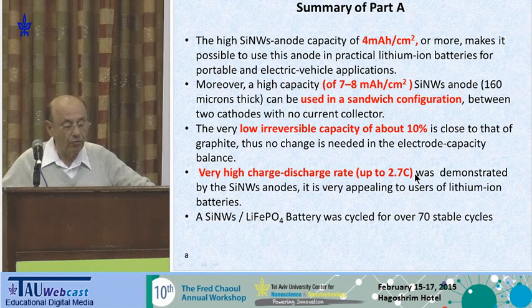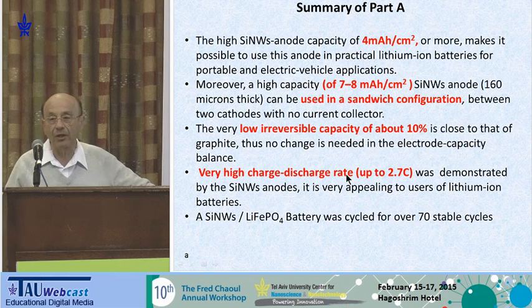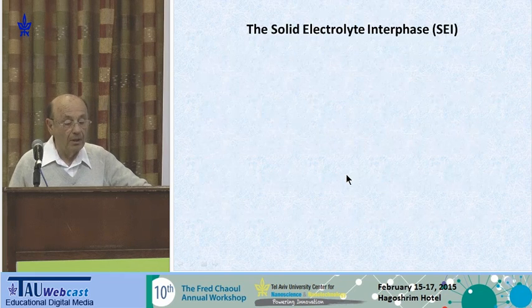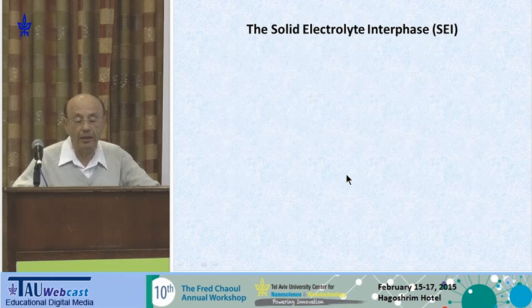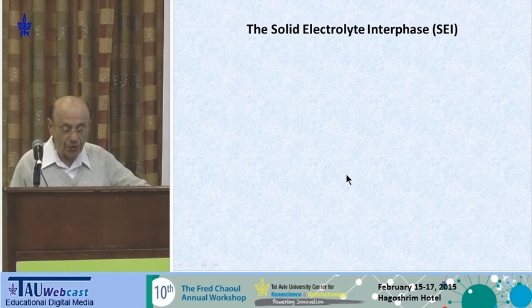I don't have time to show you, but we have shown very low irreversible capacity of about 10%. This capacity is used to build the SEI on the anode, because lithium-ion batteries are assembled in the discharged state, and when you charge it the first time, on the graphite, on the silicon, or on any anode, you first have to build the SEI. Before that, you cannot charge the battery. And we're able to run it at very high rate, so we can charge and discharge in 20 minutes. And we've also shown a battery. Now, a few words on the solid electrolyte interface, because it's a very important issue.